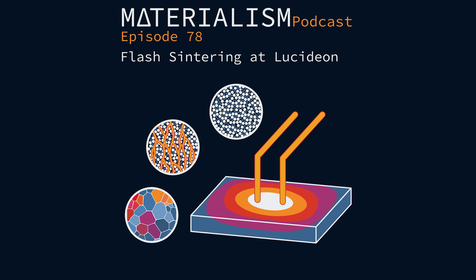So flash sintering is a material-driven process. There's not a one size fits all, right? So we have to optimize flash sintering parameters for any material. If we do, say, a 6-month study, one of the great examples that we're working on at the moment is flash sintering for nuclear waste disposition, the waste plutonium stockpile in the UK. We started off by making surrogate fuel pellets of ceria, because it behaves similarly to uranium in terms of its conventional sintering behavior. So we just make discs, we've got pellets of this, and for the first 6 months at the start we'll be blowing holes and melting the middle, right? And then we start to play with these parameters using this software, where we're teaching it the limits of the material and how to optimize that.